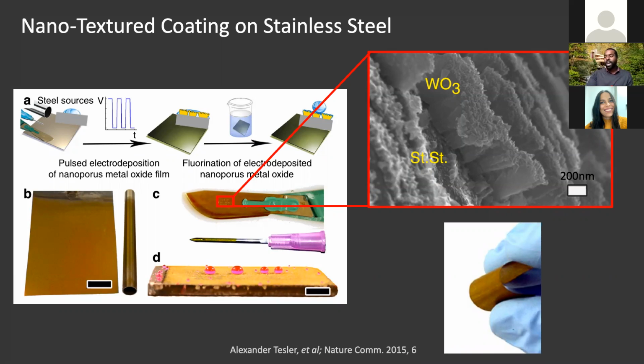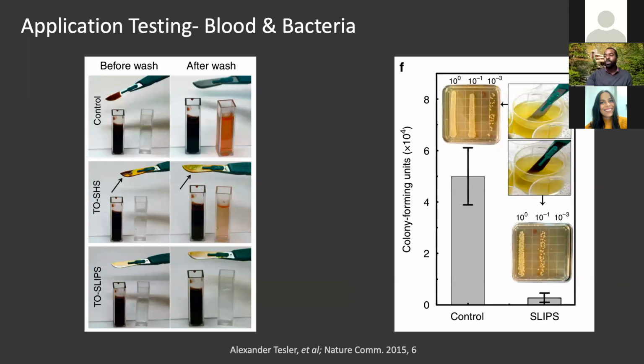And when we used this in application testing, I gave you the example of blood, we could see that when you have a control scalpel and you dip it in blood, when you remove it, there's still some blood sticking onto that scalpel. This is visualized in the washing in some water. If we have a superhydrophobic surface, which is this second case here, then you still do get some blood attaching. It's less than what you got when it was just untreated, so just hydrophilic steel. And when you have a slippery coating, which is this third example here, you get very, very little blood attached to your scalpel.